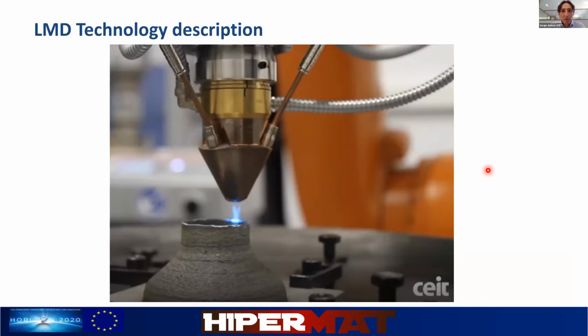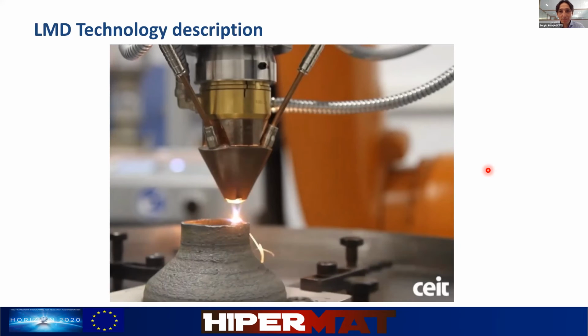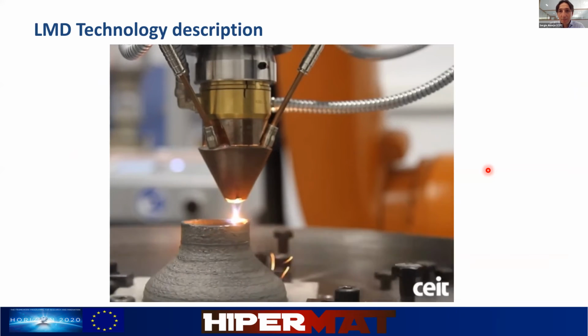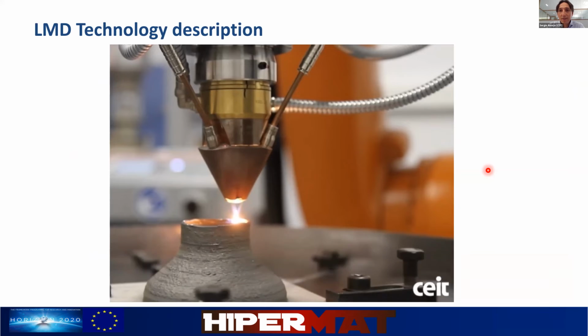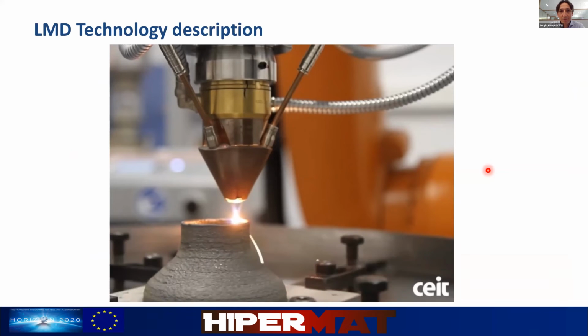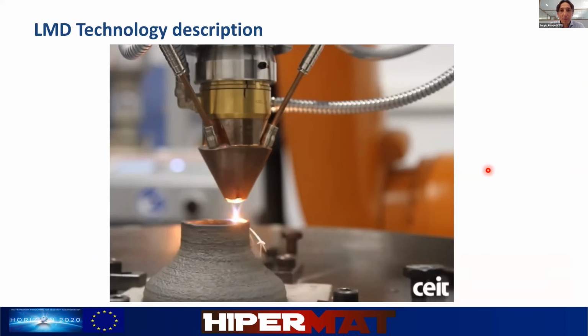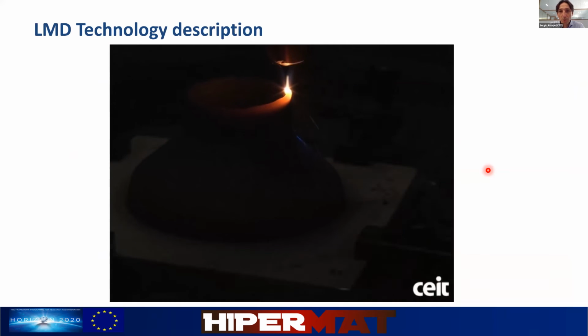We are going to see a very short video of the process. In blue, we can see the jets of powder that meet at a point, and there the laser melts the powder. The molten metal volume is usually called the melt pool or molten pool. And in this case, we see that the part being manufactured is rotating while the LMD nozzle is not moving.